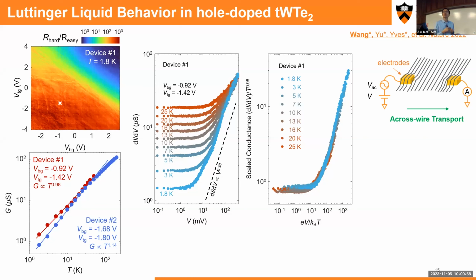And actually, I think it indicates some number of how many wire tunneling processes you might have in between this system. If you simply suggest it is a single wire system and it keeps tunneling from wire to wire, then you might anticipate some number of how many tunneling processes are equivalent to each other before it keeps tunneling to the next contact. So in this situation, it suggests you have around 30 equivalent tunneling processes.